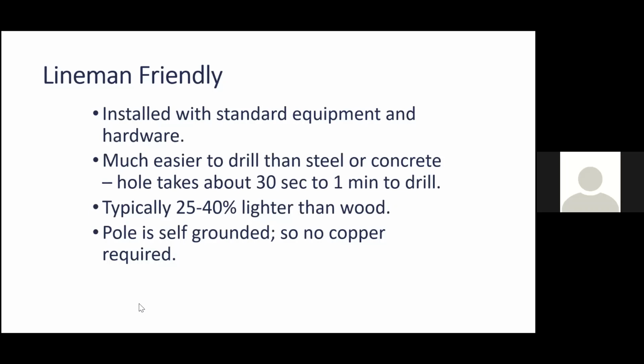As I mentioned earlier, ductile iron is lighter than wood by about 25 to 30%, 40%. We are heavier than steel by comparison, probably 15 to 25% heavier, and that has to do with wall thickness. Our ductile iron wall thickness is thicker compared to the steel. And again, our poles are self-grounded. You would not have to ground them, but as I mentioned earlier, I would recommend that you ground them as you would today with your wood poles.